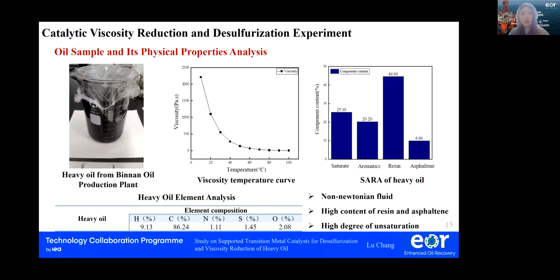And the physical properties of the oil sample are tested firstly, including the viscosity, SARA, and the element analysis of the oil sample. We can conclude that the oil sample is a non-Newtonian fluid with high content of heavy resin and asphaltene. And the degree of unsaturation of the carbon is very high.